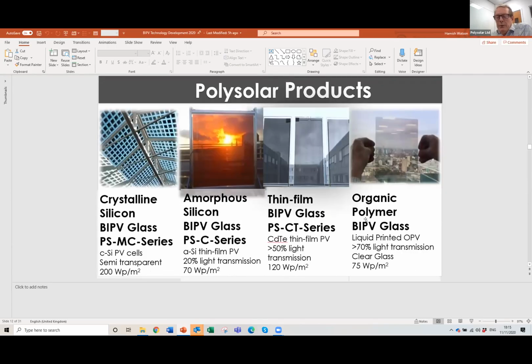In terms of what we produce as a company, we started out life with amorphous silicon. We made that transparent primarily just by putting a transparent conductive layer on the other side of the glass. And it's a technology which was developed originally by BP about 20 odd years ago. Low efficiency relative to today's technology, and has largely dropped out of the market. Was much more important a decade ago when crystalline silicon was very expensive.